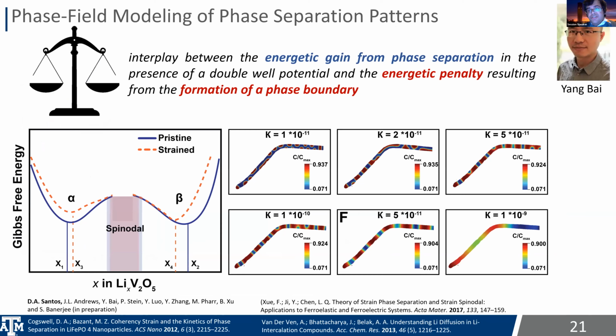And working with Baishang Xu's group and Yang Bai at TU Darmstadt, we can essentially model this quite nicely as the interplay between the energetic gain from phase separation, the presence of a double-well potential, and the penalty resulting from the formation of a phase boundary. So the specific striations that are formed reflect the energy required to form a phase boundary, multiplied by, of course, the dimension of the wire. This is why you see it in these confined particles where these striations become possible.